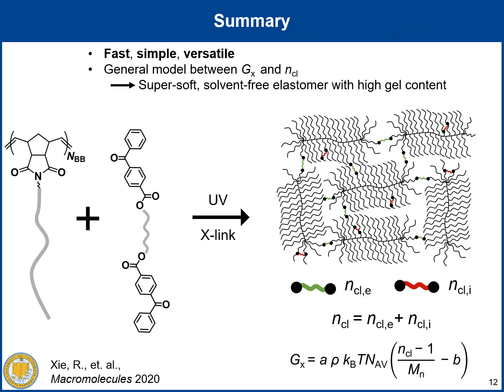In summary, we have presented a fast, simple, and versatile approach to form Bottlebrush networks, which can be well described by our general model between modulus and crosslink loading. This model provides a clear way to differentiate and quantify the number of elastically effective and ineffective crosslinkers in a Bottlebrush polymer matrix. By relying on this model, we can accurately control and predict the network characteristics of super soft, solvent-free elastomers with high gel content.